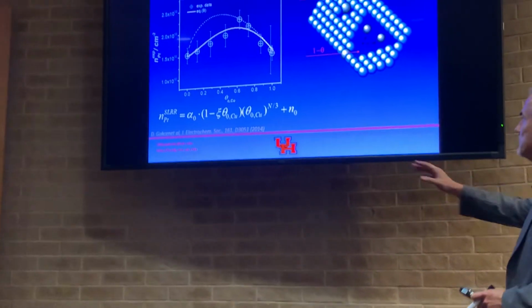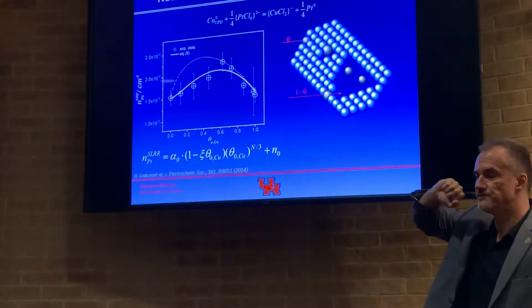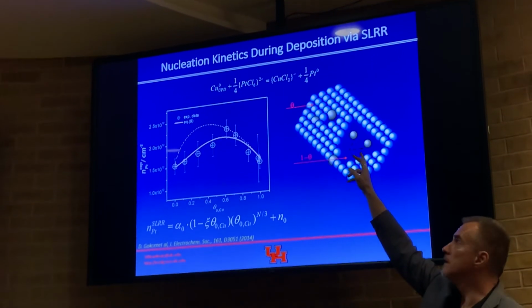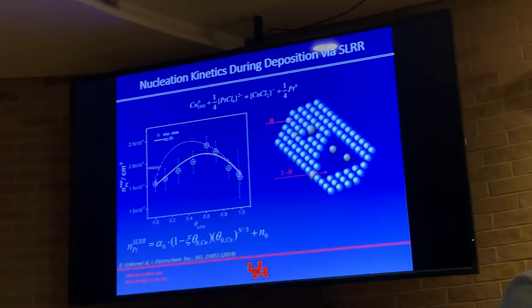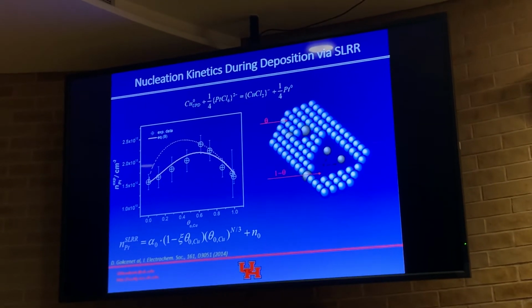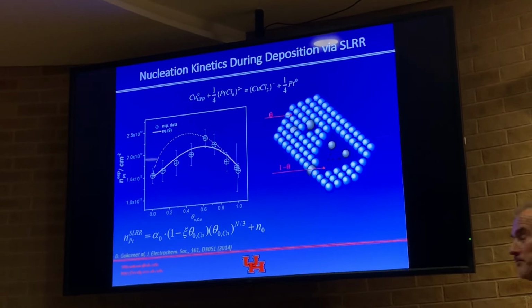And actually, I have to tell you guys, sometimes dreaming is a good thing. If you dream, you can dream your solution. So what happens here? The first scenario is that you have some free substrate surface, and a reduced platinum atom lands on the free surface, diffuses around, meets another one on the free surface, and nucleates. This is where this model applies, right? And if this is the case, no problem.